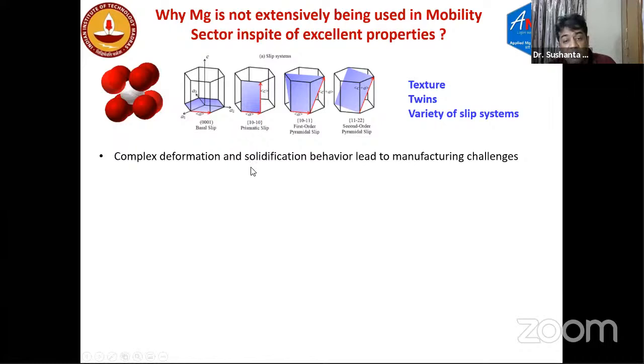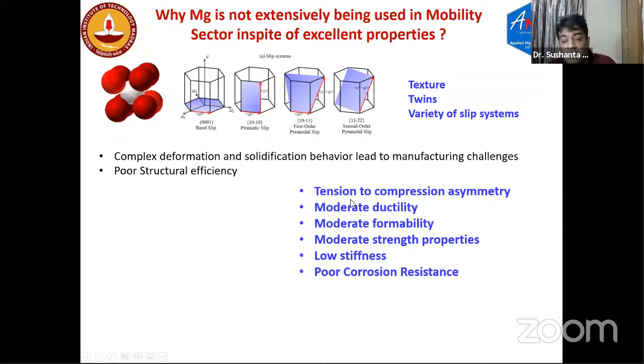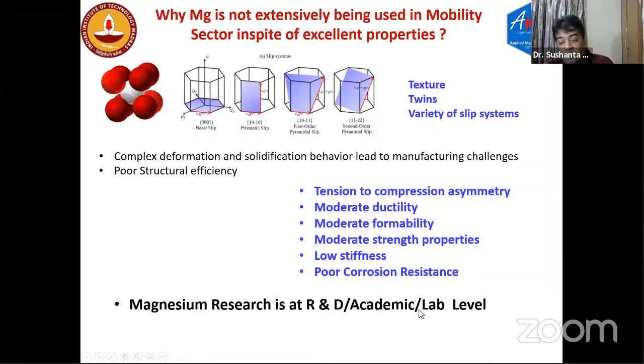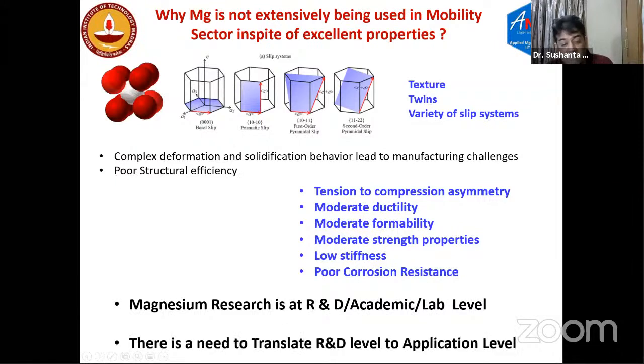Therefore, it is very difficult for the manufacturers to understand the complex deformation phenomena and solidification behavior, which lead to manufacturing challenges. And it has shown some poor structural efficiency with respect to poor tension to compression yield asymmetry, moderate ductility, moderate formability, moderate strength property, low stiffness, and poor corrosion resistance. Therefore, a lot of research work is going on to improve all the properties together, but the research work is still in the R&D lab, and therefore there is a need to translate R&D level of research to application level.